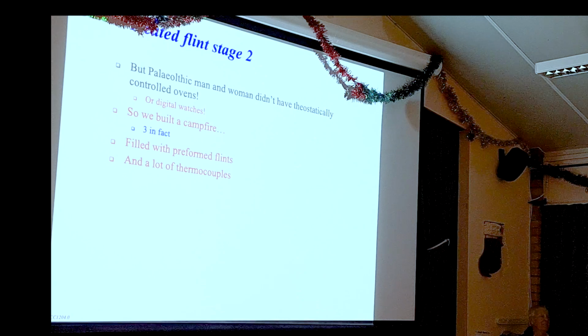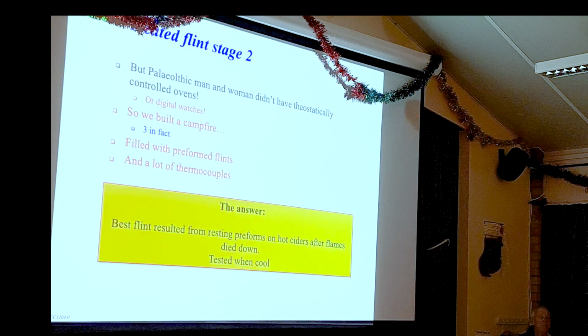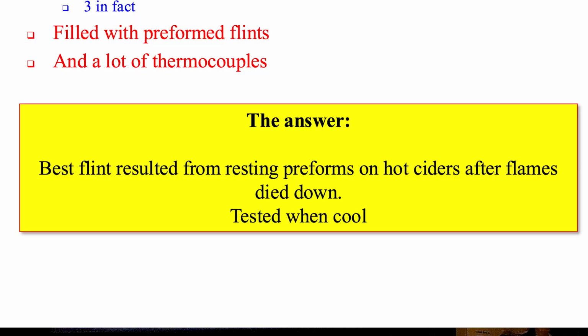And a couple of days later, they came back and said, we've got some results for you. This lot are very good, this lot are rubbish, and such like. But it turned out that the best results was when you just take the flint blanks, go to your campfire, let the flames die down, and just rest them on the top and leave them to cook. Rest them on the hot embers, which makes sense. That's the simplest way of doing it as well.